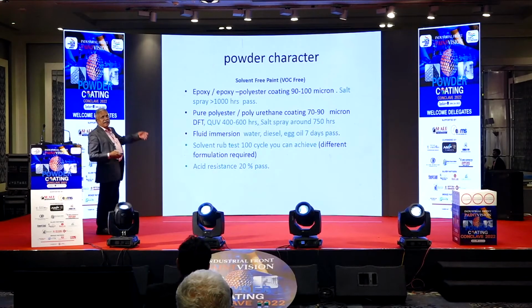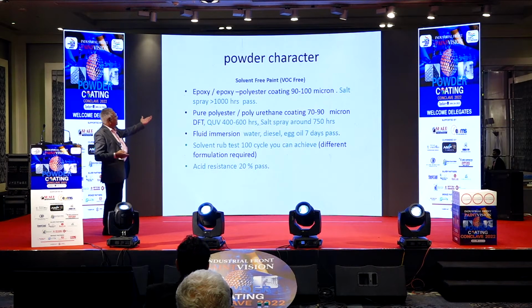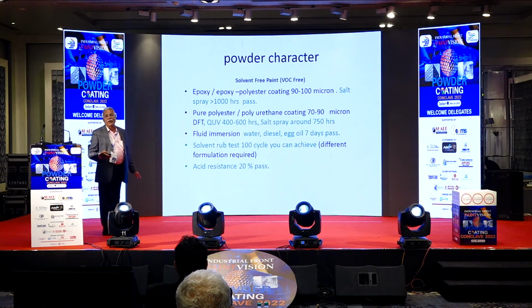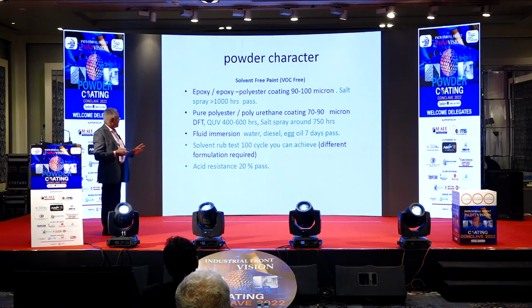So epoxy का special character क्या है? ये तो if you properly treatment made and if you apply 90 to 100 micron thickness, you will get 1000 hour salt spray, it will pass. And if you come to epoxy hybrid system, epoxy polyester, or pure polyester, pure polyurethane, you will get up to 700 to 750 hours of salt spray, and 400 to 600 hours of UV test it will pass. It will be proven one.